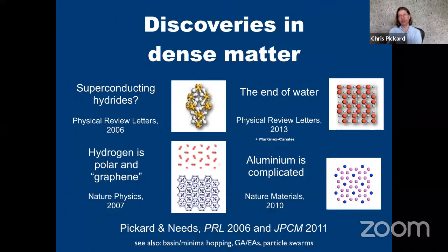And what I found very quickly with the structure searches is that we found much more stable structures than he had proposed. And part of the way that these structures have become more stable was by opening up an electronic gap. It meant I ended up with semiconducting phases at the pressure regimes where he'd proposed superconductivity, which ruled out superconductivity. But what we did find is that if you squeezed to higher pressures still, eventually, yes, you did get a metallic state. And so we were not completely negative about the idea of these hydrides being superconducting. But we realized that they would take a lot higher pressure than he was proposing. So he was proposing around 100 gigapascals, and we were saying it was going to need 200, 300 gigapascals.